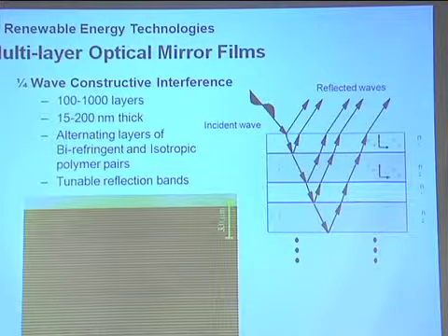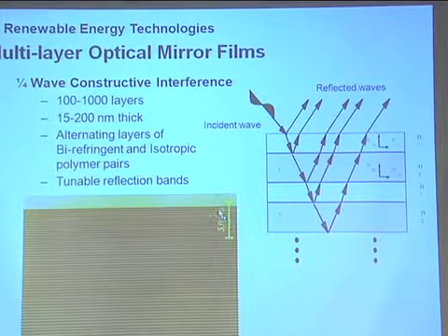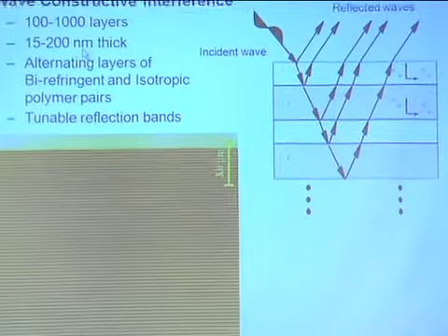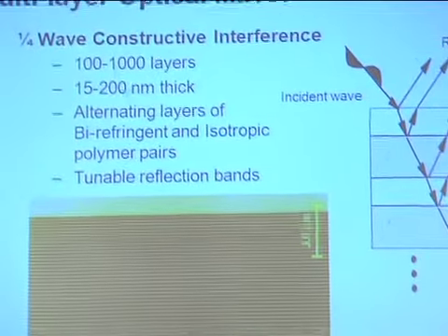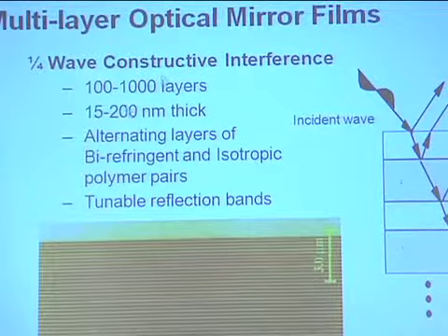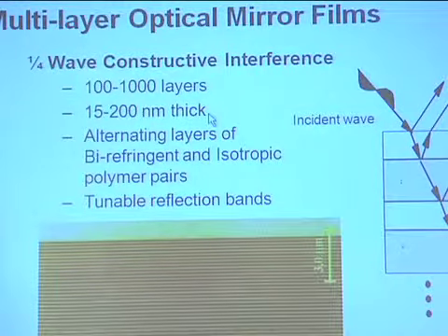And if you make those layers a quarter wavelength of the light that you want to reflect, you can get 99% reflection. And basically, every layer pair here reflects about 5% of the light. And if we're talking quarter wave of blue light, which is 400 nanometers, the layers are only 100 nanometers thick. If you're talking a quarter wave of red light, they're 150 nanometers thick.